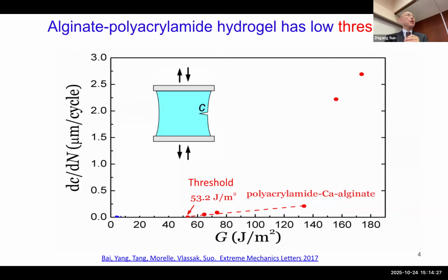So we were very embarrassed by this material. Of course, after this student graduates, there's a future student to say, we are going to correct this problem. So I'm going to talk about the correction of this problem. Oh, incidentally, I will show later that we should not be embarrassed by 50. This 50 joule per meter squared for fatigue threshold is a very common value for all polymer networks, including the gold standard, which is natural rubber, 50. We were just naive at that point.